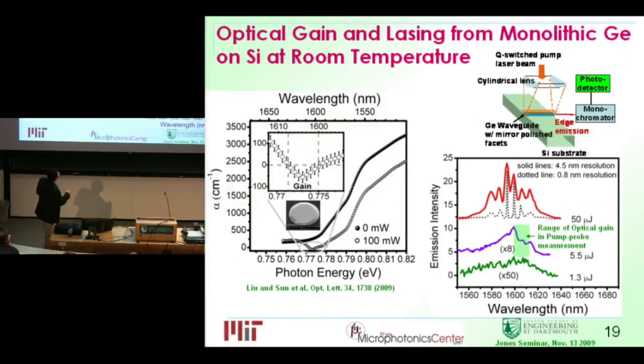And recently, we also got this optical gain result. So what is optical gain? You have a pump laser, and you population-invert the electron-hole pairs in the conduction and valence bands. Because you invert it, there's less absorption than emission, then you get a net gain in the material. So this is exactly what you see here. We're doing the experiment on a germanium microdisc. This is basically to eliminate growth defects and also to provide lateral carrier confinement. So at the same power, you generate more carriers per unit volume in this material.